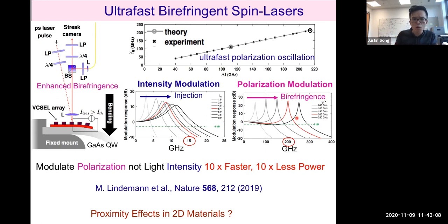Sure, but birefringence and changing your polarization does not always have to be related to spin, right? You could always have other types of birefringent behavior. So why is spin so important here? Basically, this linear birefringence can couple different helicities of light. And this coupling is then like a beating frequency. If we would try to just increase the birefringence and see what happens, the intensity of the light will remain unchanged. It will not be modulated. The mechanism for modulation of intensity of the emitted light is almost independent of birefringence.